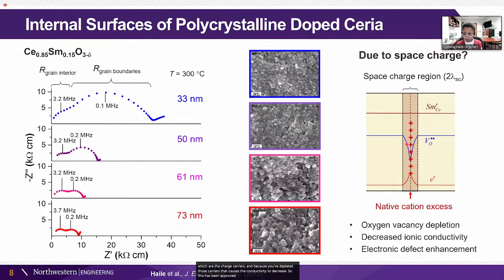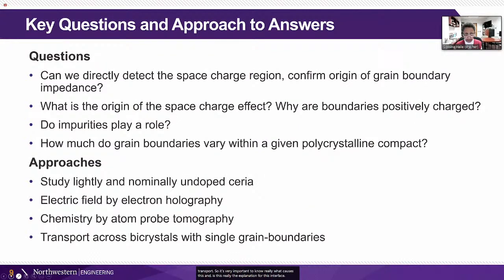So this has been the prevailing view in the literature, that there's something sort of a thermodynamic reality about these materials that inherently produces positive charge right at those interfaces. And this is also, by the way, associated with an increase in electronic conductivity, but oftentimes we don't observe that too much. What's really challenging is this decline in the vacancy concentration, and the oxygen vacancies are the carriers for the transport. So it's very important to know really what causes this, and is this really the explanation for this interfacial behavior? So what we wanted to do then was to see if we could directly detect that space charge region, and confirm that it is the origin of the grain boundary impedance.